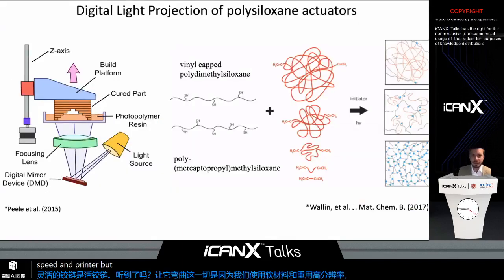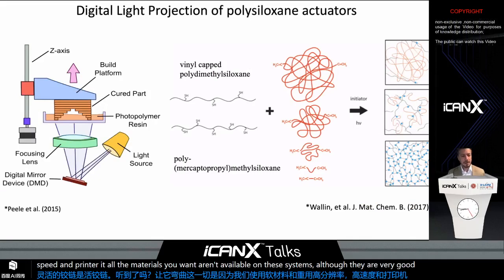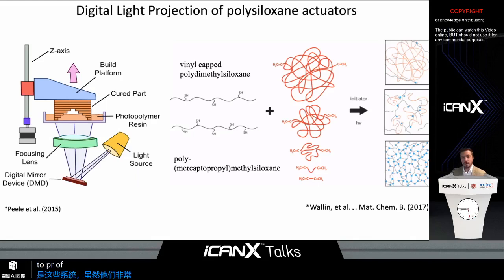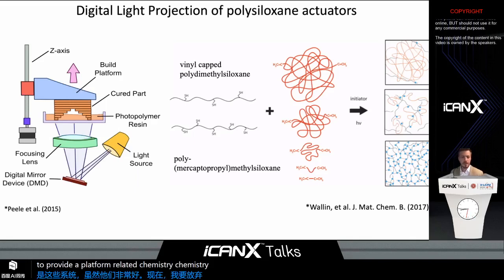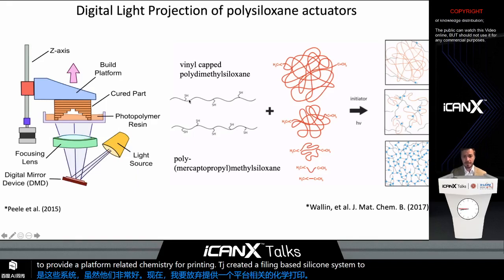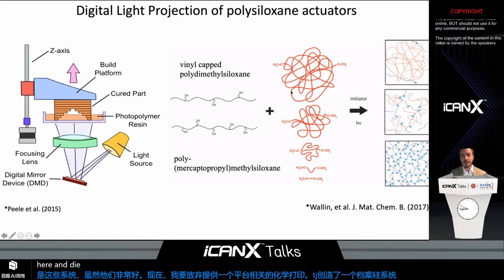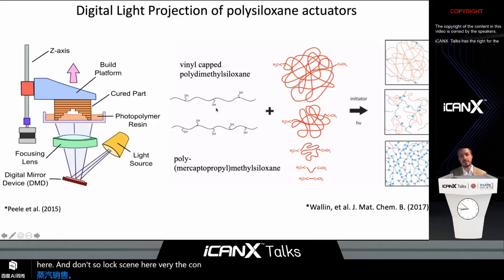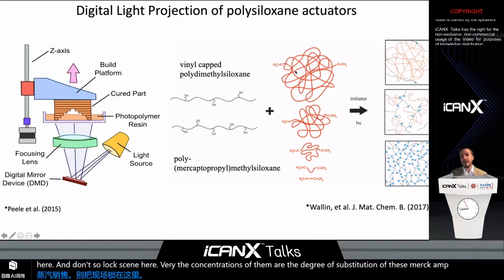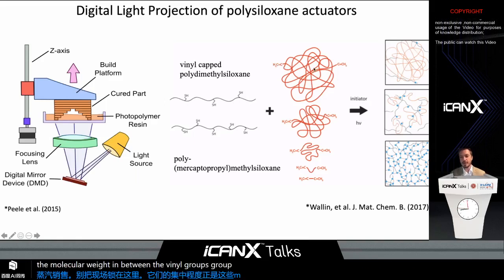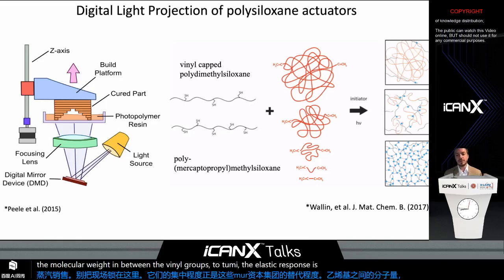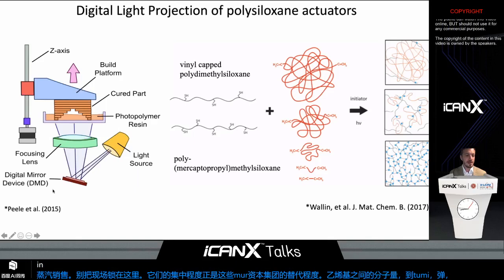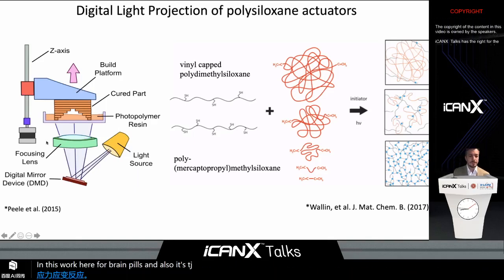But all the materials you want aren't available on these systems, although they are very good now. So to provide a platform for alternative chemistries for printing, TJ Wallin created a thiolene-based silicone system to use mercaptosiloxane here and divinyl siloxane here, varying the concentrations or the degree of substitution of these mercapto groups and the molecular weight in between the vinyl groups to tune the elastic response, or the stress strain response, of the printed structure.